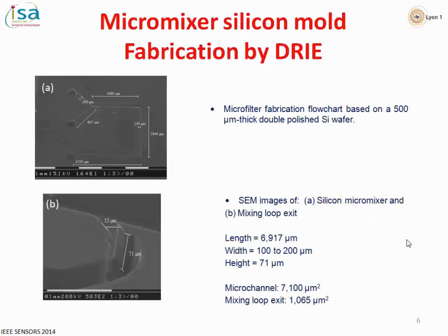Well, this is the structure that has been developed in collaboration with our colleague from CNM, from Spain. We can see clearly here this silicon in which we have several loops. This was optimized previously, because we need minor loops in order to achieve mixing. And the aspect ratio was very critical in this case, because if not, we can have some collapse and so on. Here we have some information regarding the channels, 200 at the beginning here, the input.